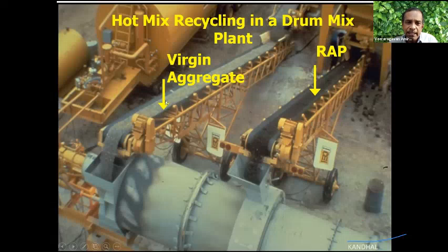So the aggregate will in turn be first heated. This hot aggregate will in turn heat the RAP. So unless this is 70%, it will not be able to heat this 30% material. Therefore, considering the plant limitation, we do not permit more than 30% of the RAP. But I have 100% RAP. How do I use it? That is the question. That's again a research need.